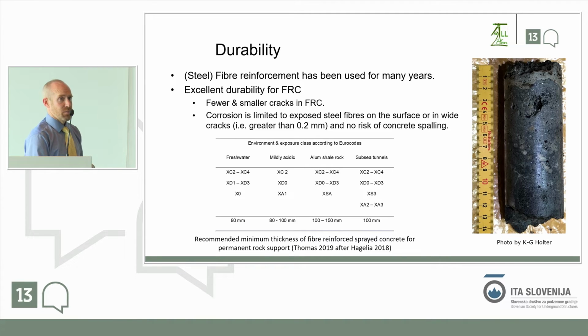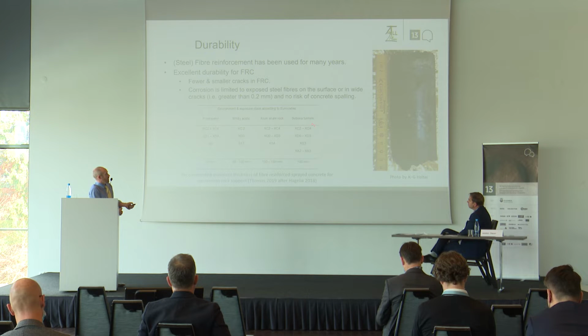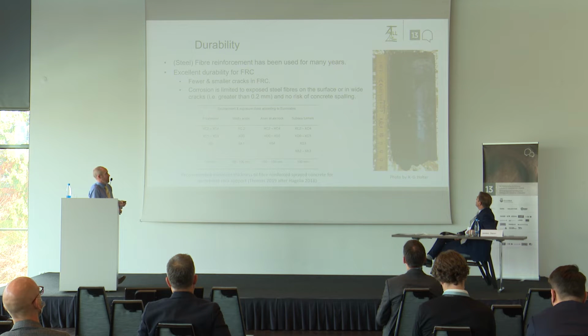So to give an example of the experience that we've had in Scandinavia, where we have tunnels with fibre-reinforced spray concrete for about 30 years really, the overall conclusion is that you can apply the normal sort of exposure classes that you see from Eurocode, and the Norwegian Road Authority has then set minimum thicknesses for their spray concrete linings to meet the durability that they need, which is typically 100 years. And you can see that generally ranges from 80 millimeters in a standard case, but if it's a subsea tunnel where you've obviously got a more aggressive situation, it's more like 100. And that's a sample from one of these tunnels. It's 22 years old, and it's in very good condition.